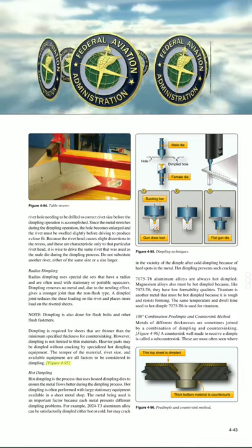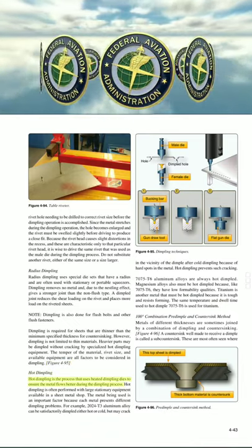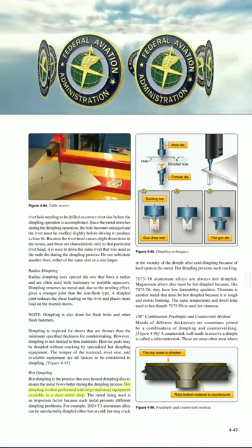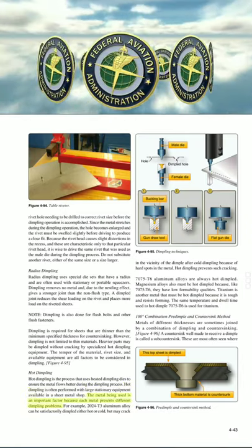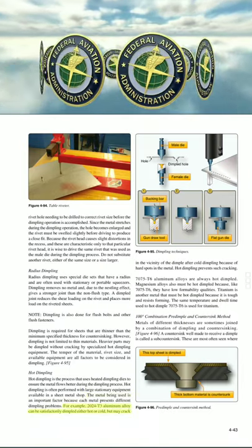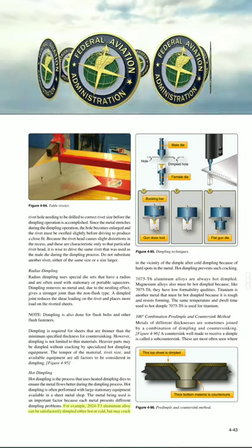Figure 4-95. Hot dimpling. Hot dimpling is the process that uses heated dimpling dies to ensure the metal flows better during the dimpling process. Hot dimpling is often performed with large stationary equipment available in a sheet metal shop. The metal being used is an important factor because each metal presents different dimpling problems. For example, 2024 T3 aluminum alloy can be satisfactorily dimpled either hot or cold, but may crack